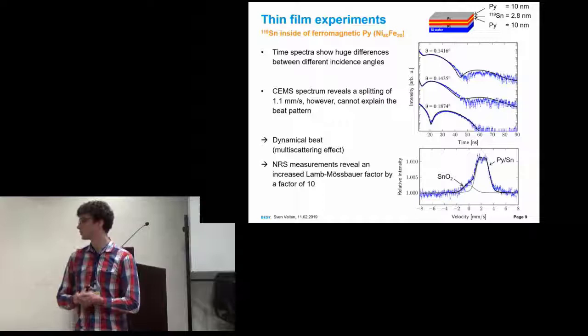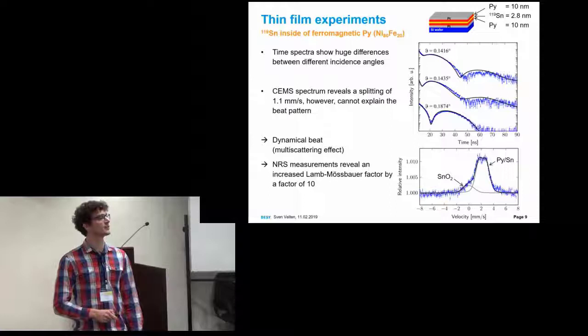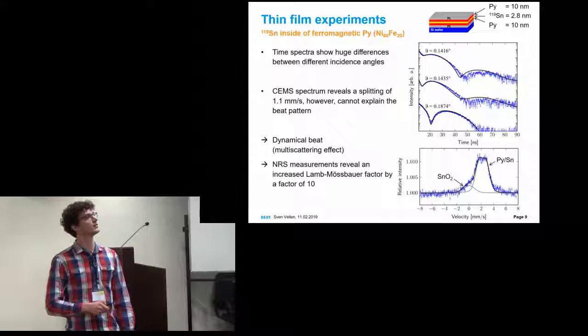From 0.04 to 0.4. This is quite interesting. The reason for this, we don't know yet. There might be that we don't have beta-tin anymore - crystal changes inside of such a small layer. Or there might be also some confinement of the phonon density of states.